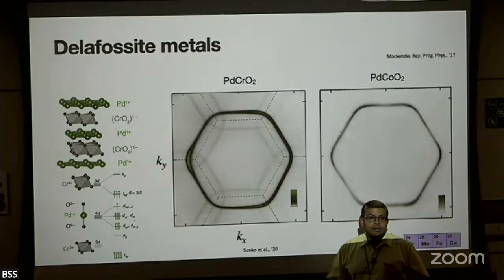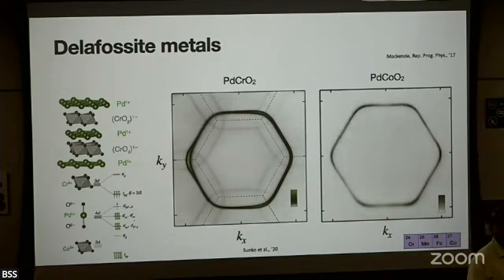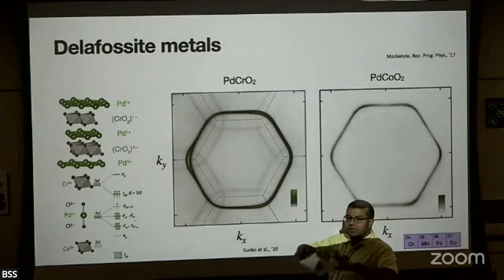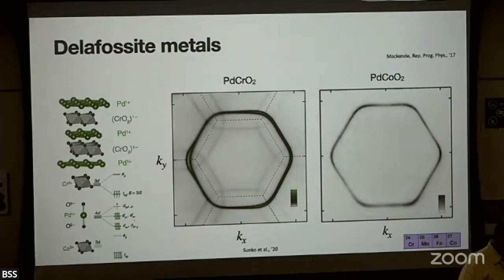Chromium oxide, on the other hand, is a Mott insulator. Okay, so it's a triangular lattice, again, which has local moments sitting at the sites of the triangular lattice. Now at low temperatures, the fact that you see these shadows has to do with the presence of these local moments. I will not get into the detailed description of that. I can talk about that offline. Now, chromium and cobalt, if you remember your periodic table, they're pretty close by. So their ionic masses are quite similar, which means if you look at the phonon spectra of these two materials, they're also reasonably similar. Any questions about the material?